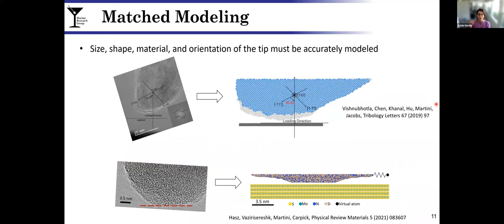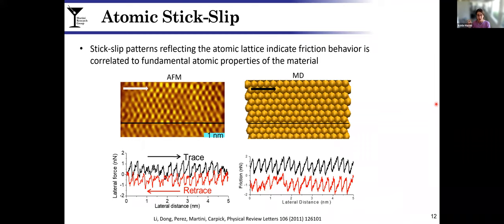A key feature about designing experiments and simulations together - friction involves two things. It involves two bodies in sliding relative motion. So designing a model of an AFM experiment must necessarily capture not only the structure of the sample being measured, but also the tip, including its structure, shape, crystallographic orientation, and so on. But once you do that, you can really get pretty good matching results.